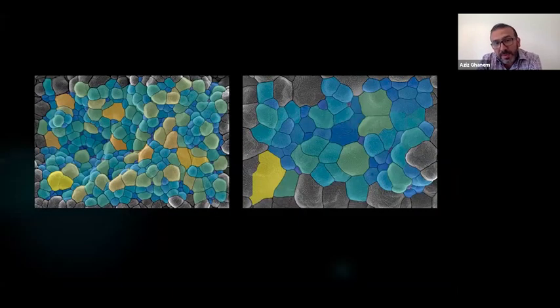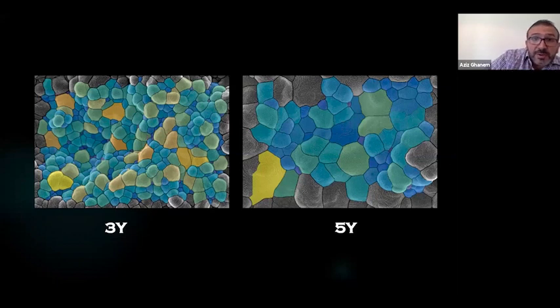Right. This is an SEM image that has been done for both of these zirconias, and both are at the same magnification. On the left-hand side, it is a 3Y zirconia, and on the right-hand side, it is a 5Y zirconia. I talked a lot about dopant, the effect of yttrium, and about the grain size. Okay, so the smaller the grain size, the more grain boundaries, as you can see in these SEM images. All these boundaries will cause the light to diffract, okay?